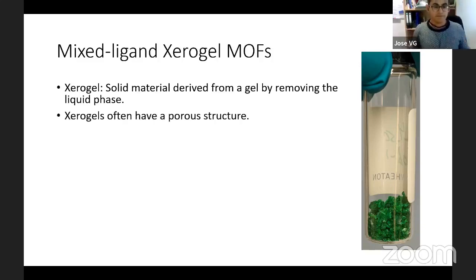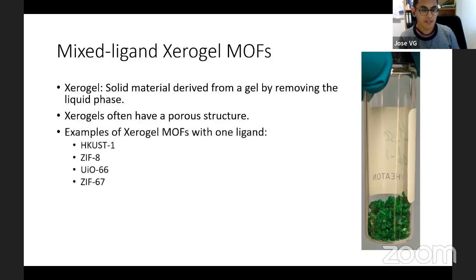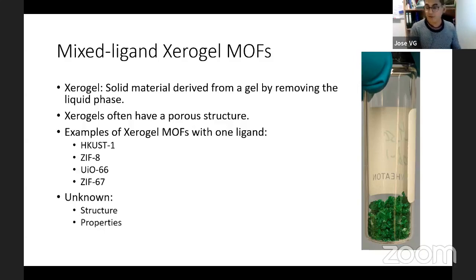These xerogels usually have a porous structure, regardless of whether the MOF is porous or not. And some examples of other xerogels, recent xerogels, have been HKUST-1, ZIF-8, UiO-66, ZIF-67. And practically it's almost, I don't know, 80% of the published xerogels so far. So there is no more. However, this xerogel is composed of two ligands. So it could be the first mixed ligand xerogel. However, we don't know so far the structure, and we know very little about the properties of this material. So this is another possible work for the coming students.